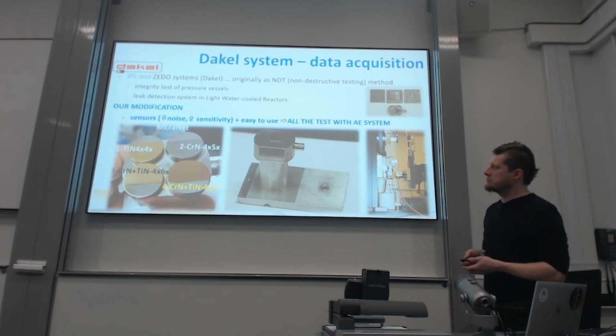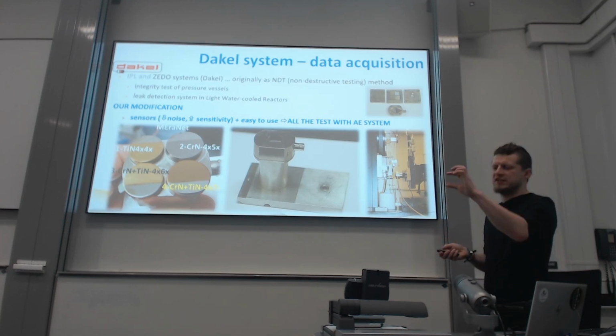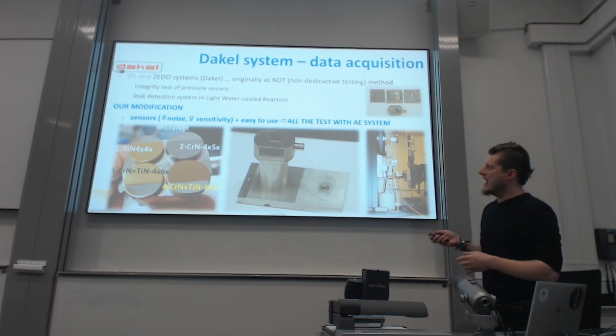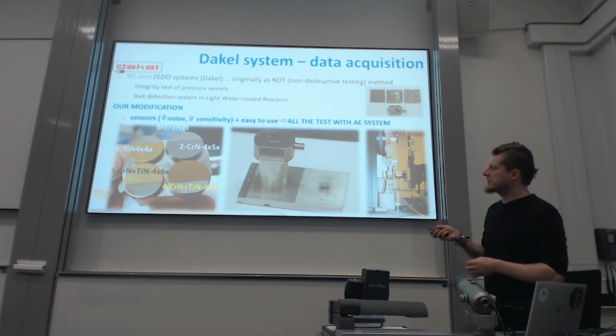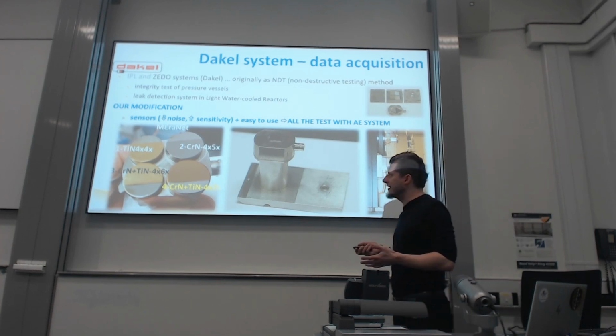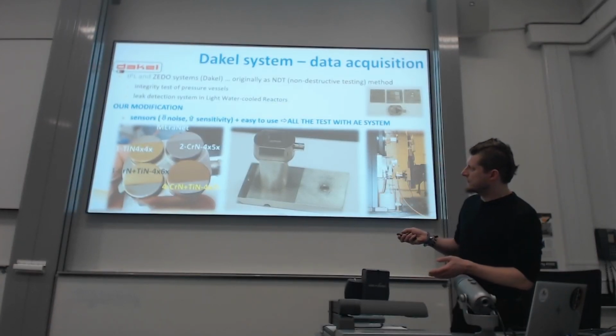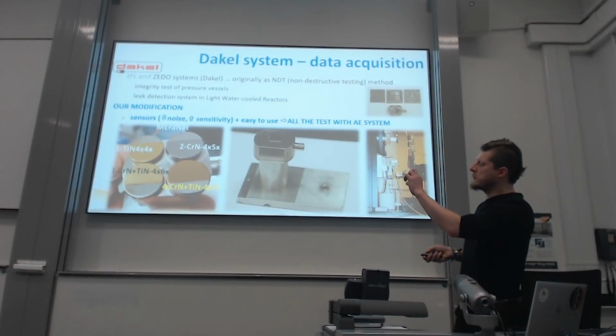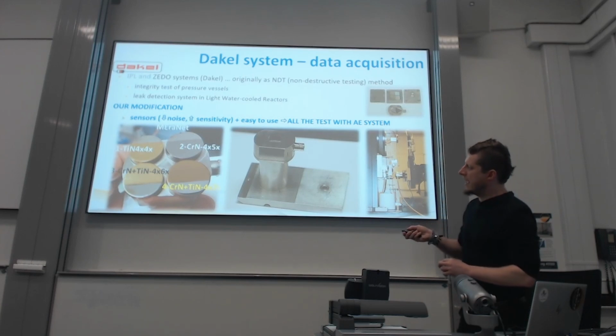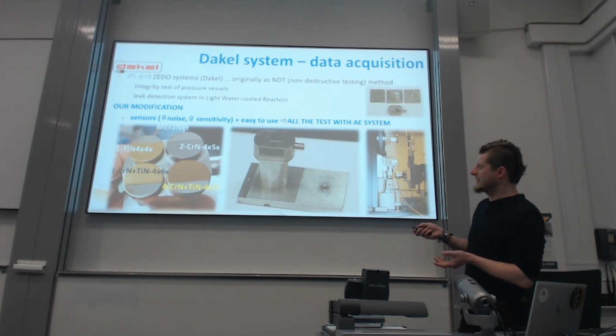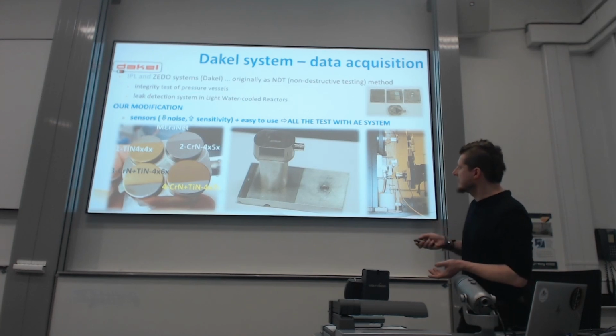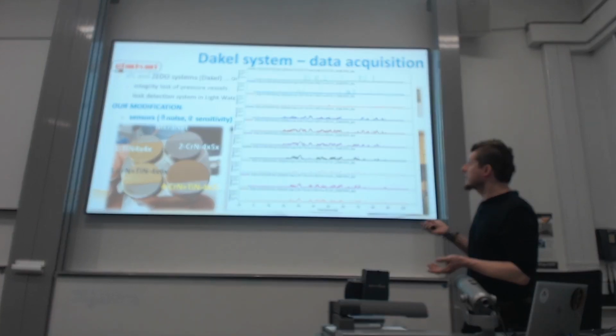This is probably the biggest sample we have measured. Some metallic stuff like 2 centimeters, and some titanium nitride coating, chromium nitride, titanium nitride coating combined. So actually there are several interfaces. This is like 4 multi-layers. Now the quite thick metal and the wax, then the metallic part, and the sensor is inside. And these are the results.